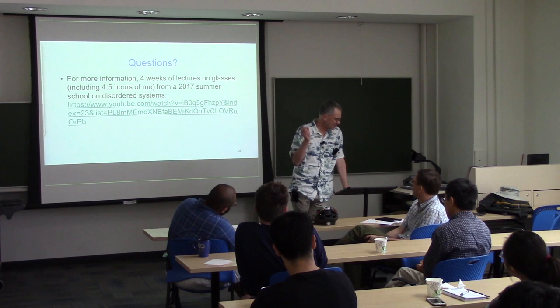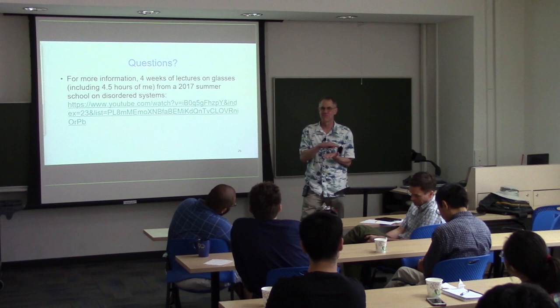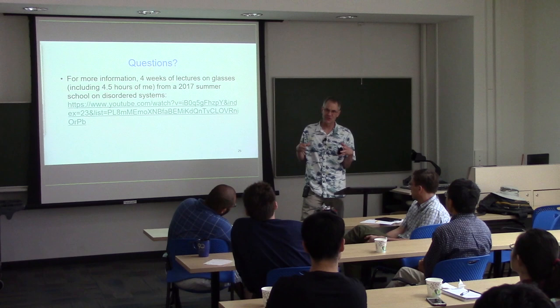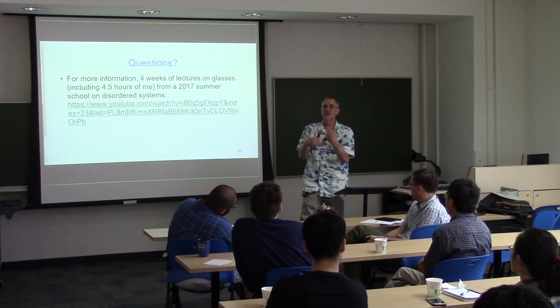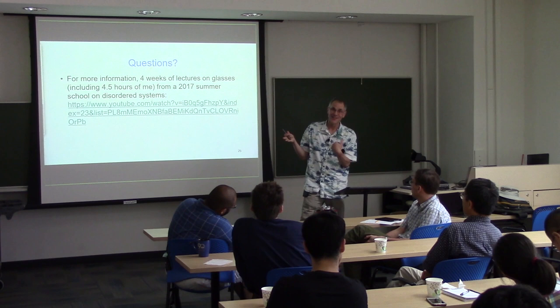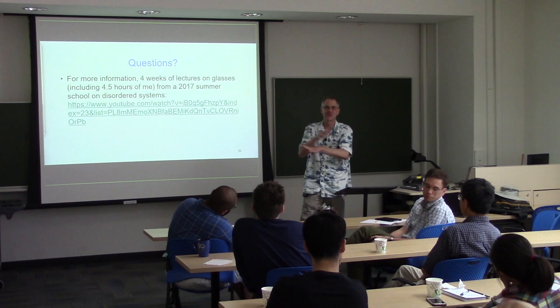Something new has happened in vapor deposition in the last 10 years, because everybody assumed that what you said was true. But it turns out there's something else going on, and that is that glasses have mobile surfaces. If you're holding your substrate at, say, 85% of Tg, what you said is true, you very quickly quench from whatever temperature the molecule had to the substrate temperature. But there's enough mobility at the surface, maybe a million times more than you expected in the bulk, that while these molecules live for 10 or 20 seconds before they get buried by other molecules, they're swimming around and sampling, and that's the key.